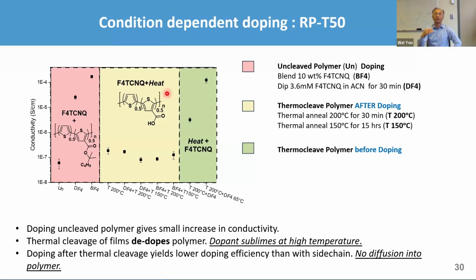Now you say, what about heating the polymer film, removing the side chain, and getting the side chain free polymer? Then you put in F4TCNQ. But after heating and removing the side chain, your polymer film becomes so insoluble that essentially no diffusion can occur from F4TCNQ into the polymer film. That's why very little doping can occur. So you won't be able to get a high conductivity either.